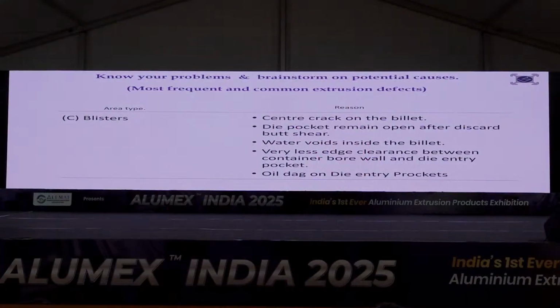Then the die pocket remains open after shearing. When your shear blade condition is not good, or there is a gap between your die and shear, or your die is shaking, or your discard is very long or very short, at that time some part of the pocket gets opened. And when the next billet tries to enter that gap, there is air entrapment. That also gives you a blister problem.